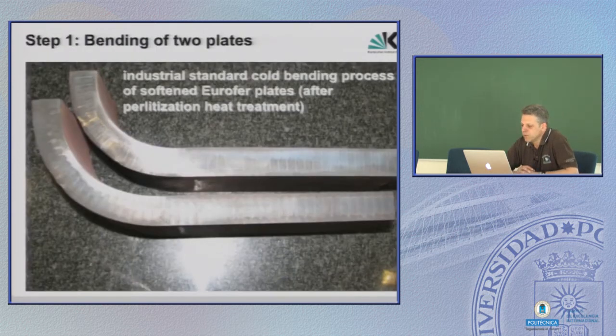And now you have to remember a few things I mentioned yesterday. If you want to bend massive thick Eurofer plates, that's not so easy, depending on the bending radius. What we have done here is we have performed a heat treatment step on the Eurofer, in such a way that the Eurofer does not transform into martensite, this hard and strong material, but we use a very low cooling rate, and in that way it produces pearlite. And pearlite, if you remember, is very, very soft and therefore easy to bend. And this is one of the advantages of chromium steels.